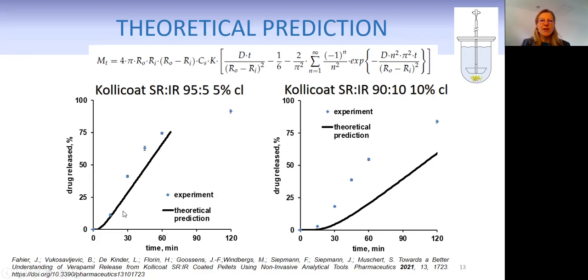So, you can see when we predict drug release in the case of 95-5 blends, we've got a good correlation in the beginning, but then the drug release theoretically obtained underestimates the one from the experiments. The model also takes into consideration a lag time, meaning we've got a drug-free coating through which water first needs to go into the core, which actually fits quite well. But especially with the 90-10 blend, you can see that the theoretical prediction clearly underestimates the real drug release obtained from the pellets. So diffusion is not the primary drug release mechanism with these types of pellets.